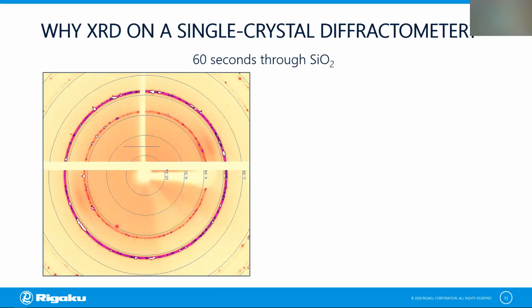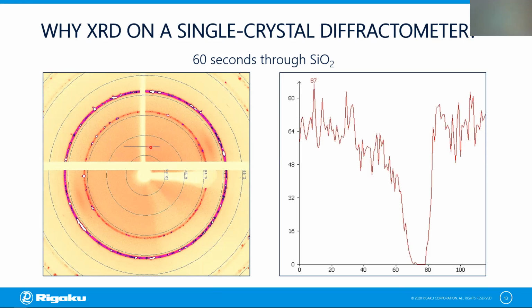So how does that translate into diffraction images? I have two examples to show you. The first example is a diffraction image obtained from silica, which I exposed to the copper beam for 60 seconds. And on that image, I drew a horizontal line here, which gives me access to a two-dimensional plot of the intensity distribution along that line. And you see the line crosses over the beam stop shadow.